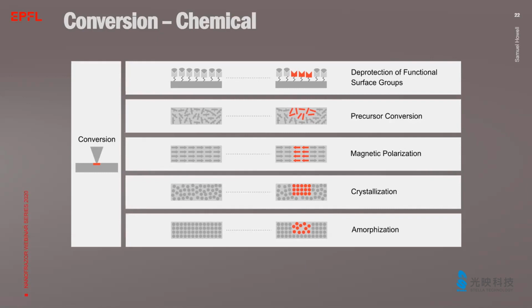Another technique that has been often used in literature is the local conversion of a precursor material into a functional material. A few examples are reduction of graphene oxide to create conductive nanocircuits of reduced graphene oxide, or the fabrication of organic semiconductors from a precursor material. Recently, a new unique application of TSPL has emerged, where heat from the tip is used to locally modify polarization of magnetic domains by heating magnetic multilayer films under application of an external magnetic field. Another example is crystallization of nanoscale areas with a heated tip. And here, chalcogenide films are best suited for such applications.